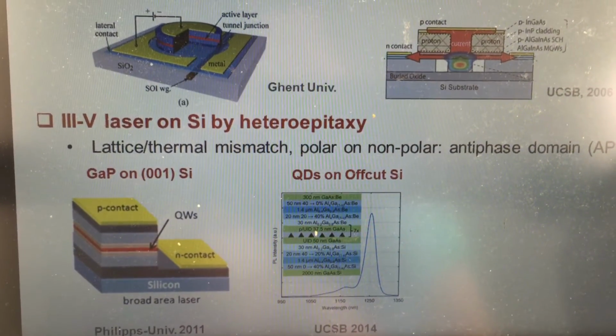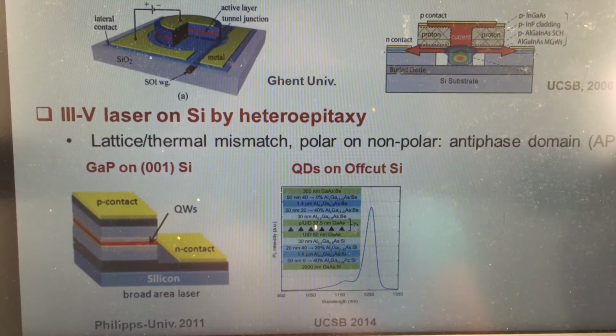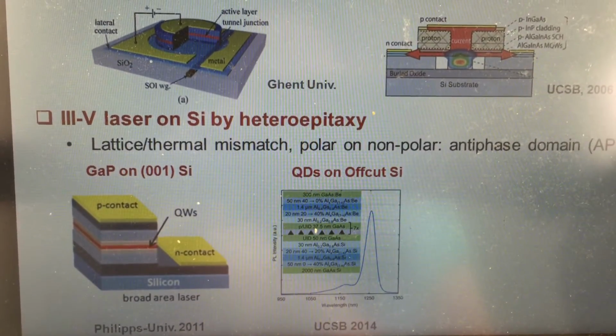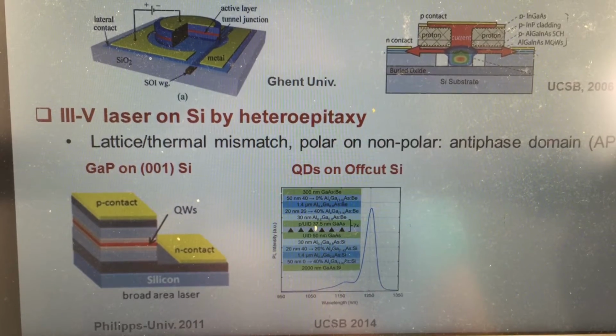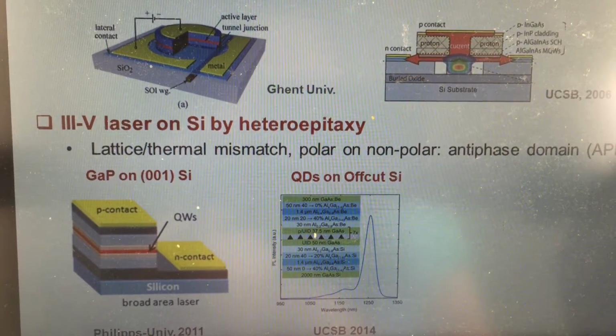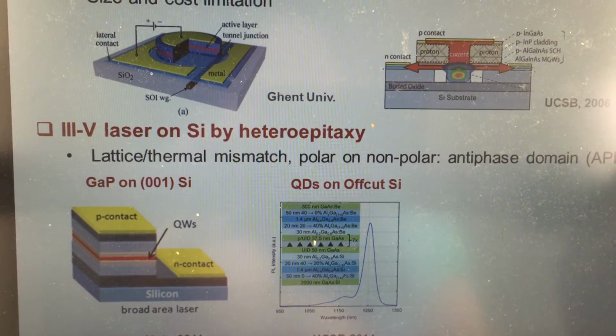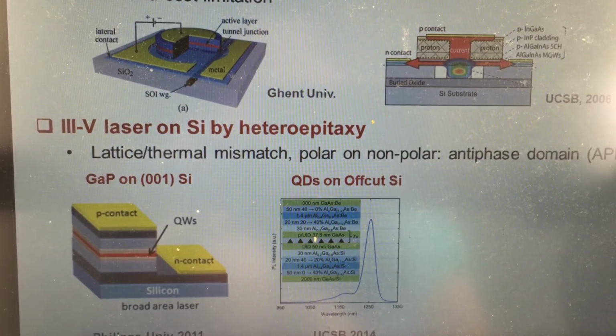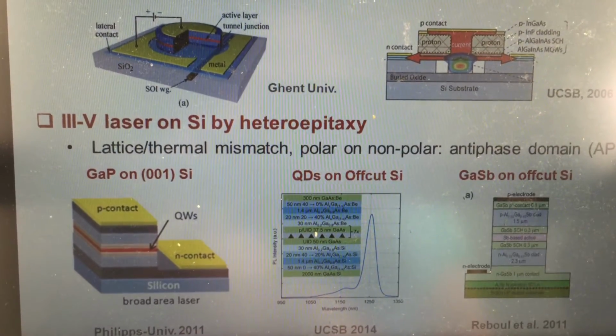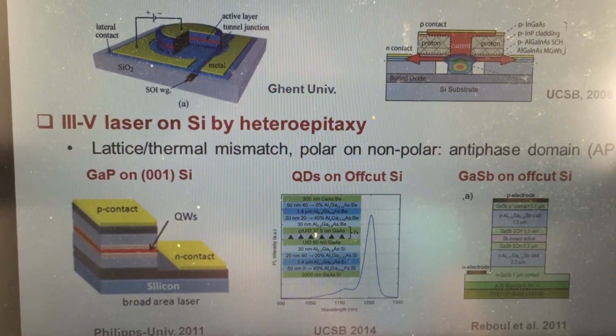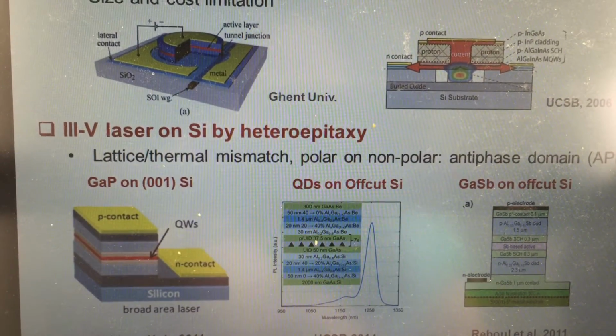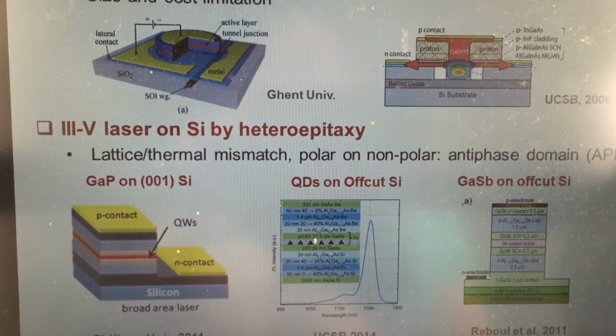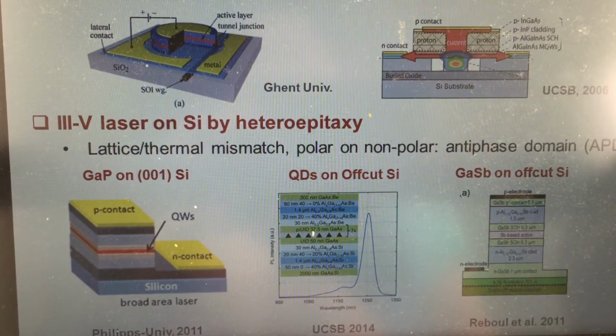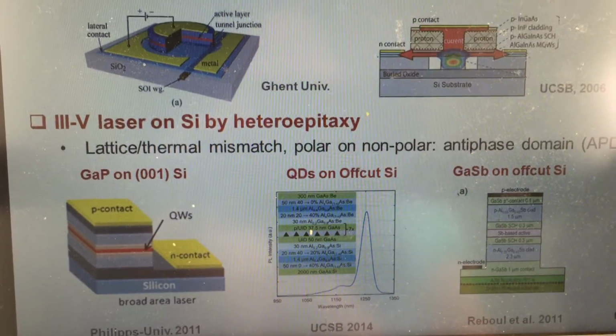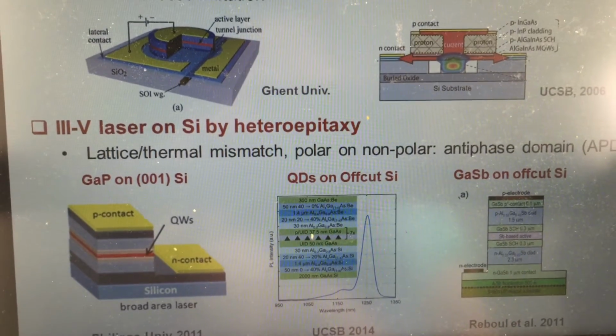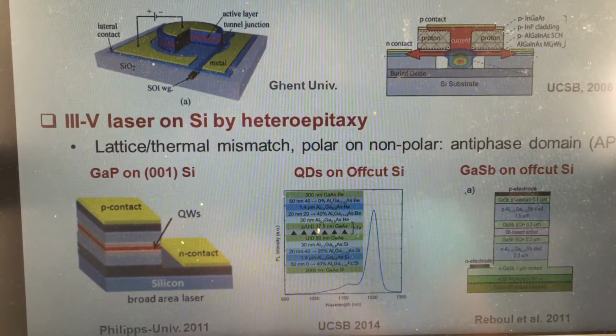Well, really high-performance 1.3 micron quantum dot lasers has been achieved. The 3-dimensional nature of the quantum dots are less vulnerable to defects, leading to improved performance and prolonged lifetime for lasers. However, just like the gallium antimonide material system, these 2 kinds of lasers are exclusively grown on the off-cut silicon substrate, thereby compromising their full compatibility with the mainstream silicon CMOS manufacturing.